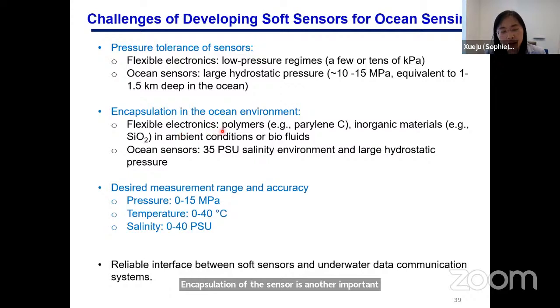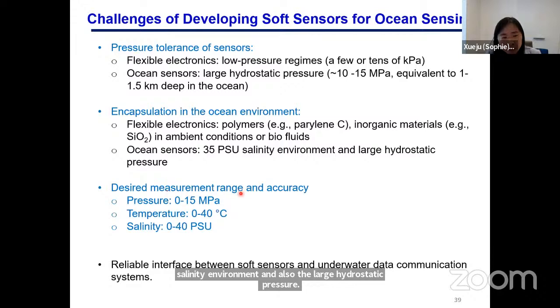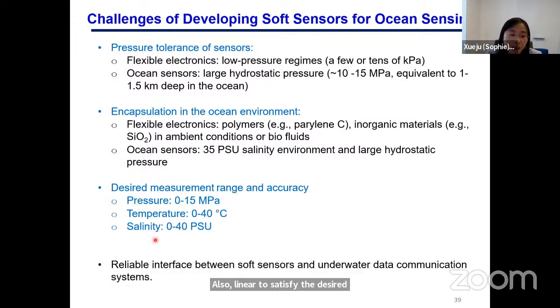Current flexible electronics are usually encapsulated with polymers, inorganic materials for operation in ambient conditions, like for wearable devices, or in biofluids, like implantable devices. But ocean sensors need to survive the saline environment and also the large hydrostatic pressure. Also, they need to satisfy the desired measurement range, for example, the high pressure, temperature, and salinity.